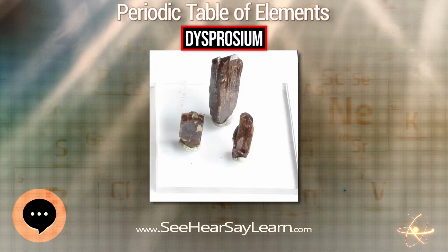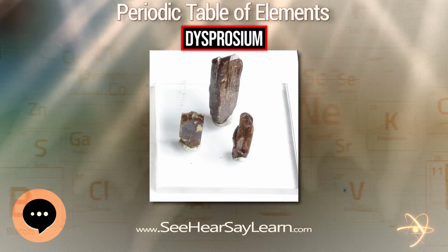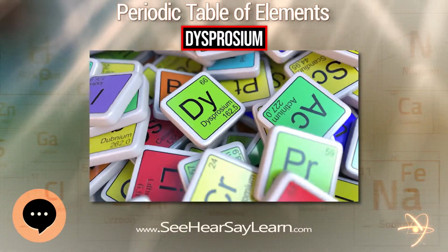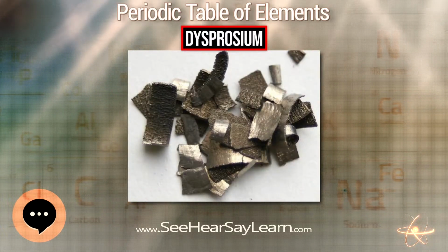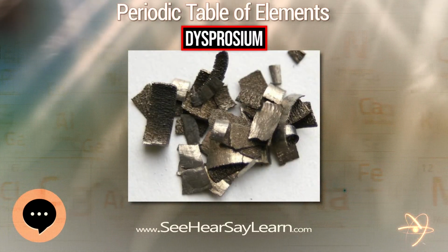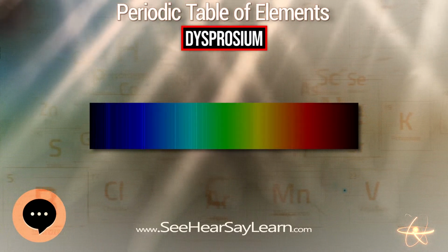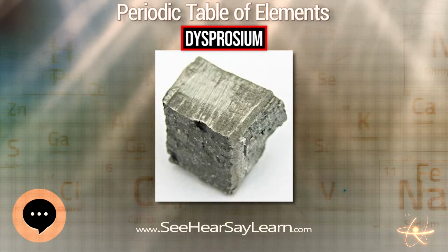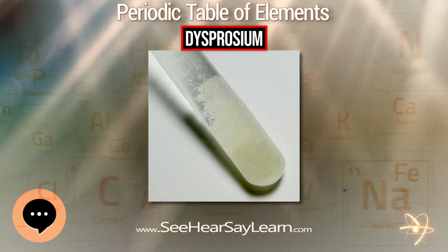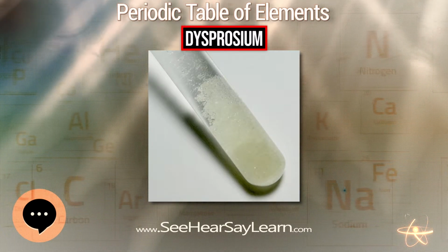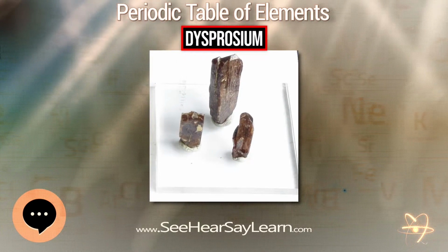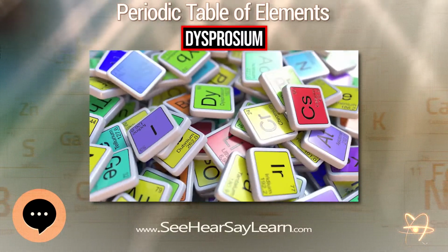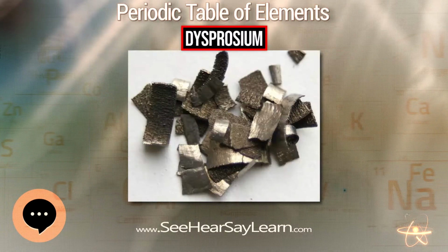Because dysprosium and its compounds are highly susceptible to magnetization, they are employed in various data storage applications, such as in hard disks. Dysprosium is increasingly in demand for the permanent magnets used in electric car motors and wind turbine generators. Neodymium iron boron magnets can have up to 6% of the neodymium substituted by dysprosium to raise the coercivity for demanding applications, such as drive motors for electric vehicles and generators for wind turbines. This substitution would require up to 100 grams of dysprosium per electric car produced. Based on Toyota's projected 2 million units per year, the use of dysprosium in applications such as this would quickly exhaust its available supply.